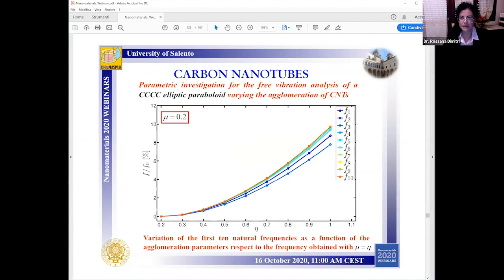So here we plot the first natural frequencies versus the agglomeration parameter eta, where we keep fixed the ratio mu equal to 0.2. And here we analyze the case where mu can be lower or equal to eta, which means that carbon nanotubes can be both included in the inclusions and scattered in the polymer matrix. So each frequency here, reported in a relative form with respect to F0, the frequency when mu is equal to eta, seems to increase monotonically for an increased value of eta, which corresponds to a varied stiffness, of course, of the material and the structural element.